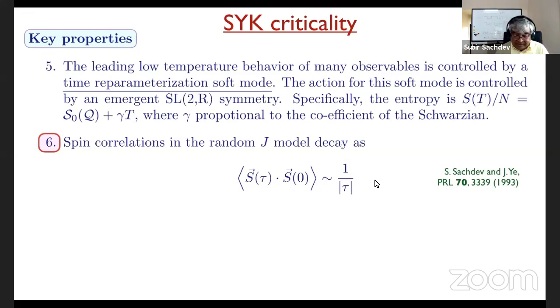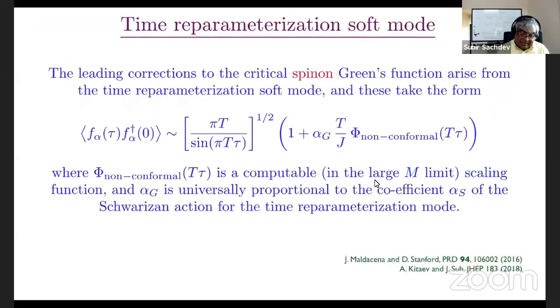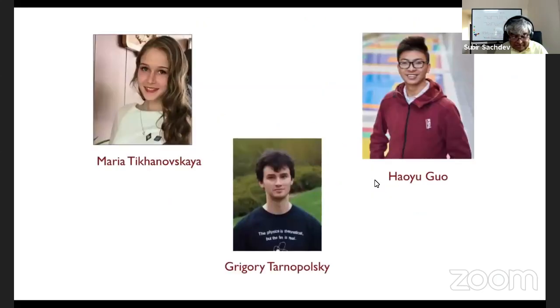So one example of this, which was already in these papers, is for the SYK model, where the corresponding statement would be to look at the correlation function for the spinons. In that case, it has an exponent 1/2. At finite temperature, you get this form from conformal invariance. That was understood by George and Parcollet already. And then you have these corrections coming from irrelevant operators. And the dominant irrelevant operator, which also gave the leading correction to the entropy, is this time reparameterization mode for this model. That gives you a correction that's linear in temperature or linear in frequency, depending on which regime you're looking at. So there's some scaling function here which in principle can be computed. The only unknown here is alpha G, but this alpha G is related, in fact, to the gamma.